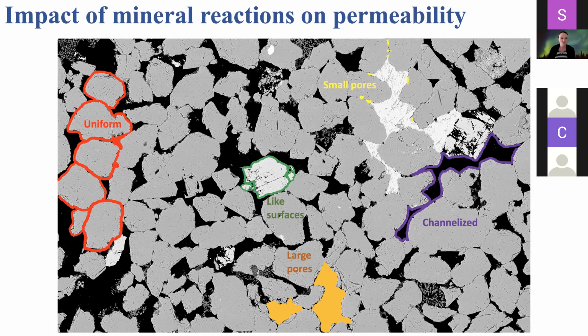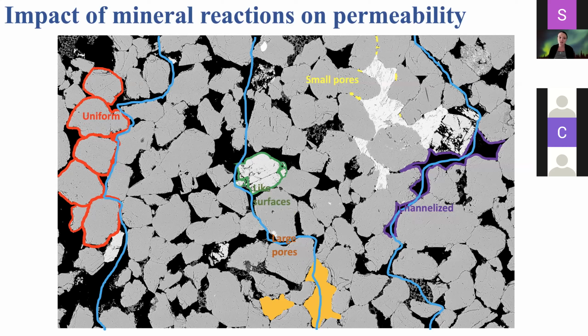In some cases, we have seen that mineral reactions occur uniformly on all grain surfaces, like shown in red here. We've seen other systems where reactions occur preferentially along a flow path, like in channelized flow, shown in purple. In other cases, only some mineral surfaces are impacted. So if you only have some reactive minerals, or if minerals preferentially precipitate on like mineral surfaces, like shown in green. And in some cases, mineral reactions are controlled by pore and throat sizes and occur preferentially in small or large pores, or are inhibited in small or large pores. And you can imagine that these variations in the spatial distribution of reactions might have different impacts on the permeability evolution of the system.